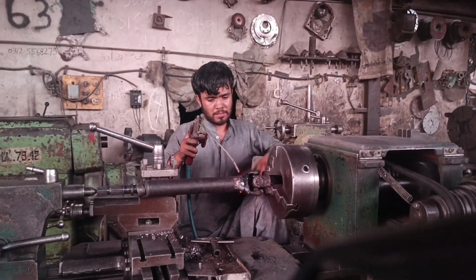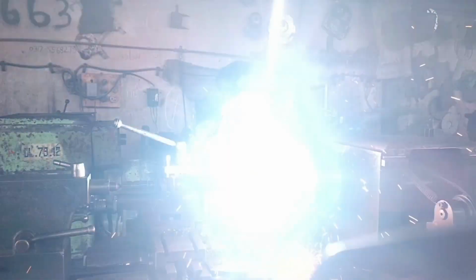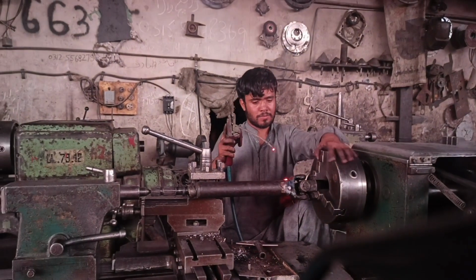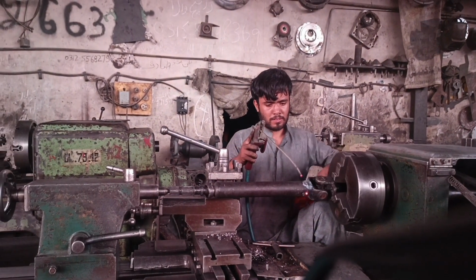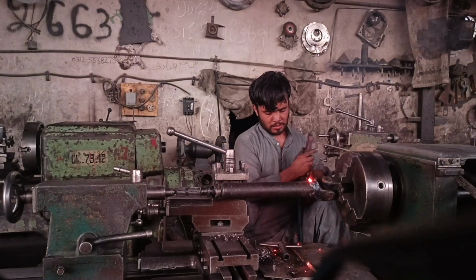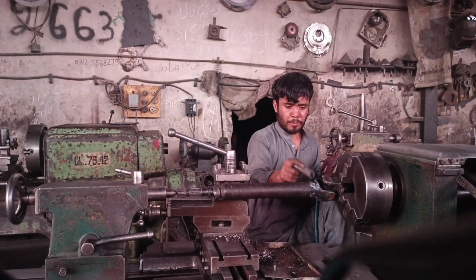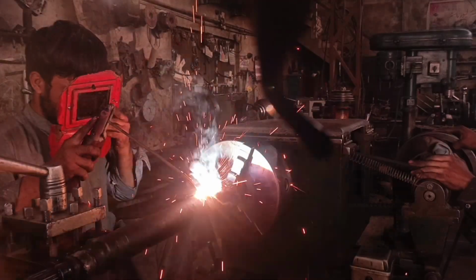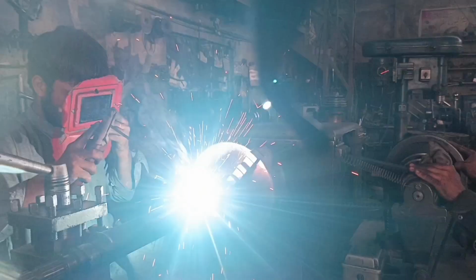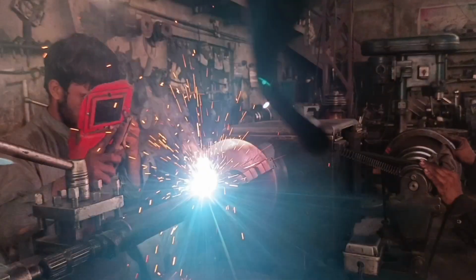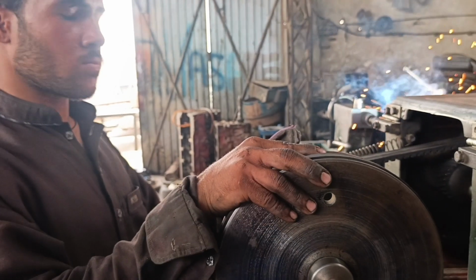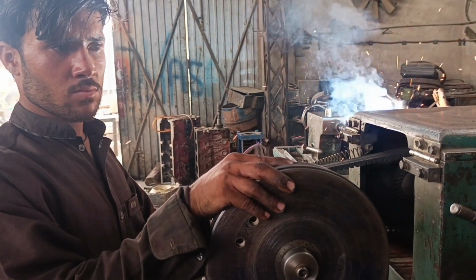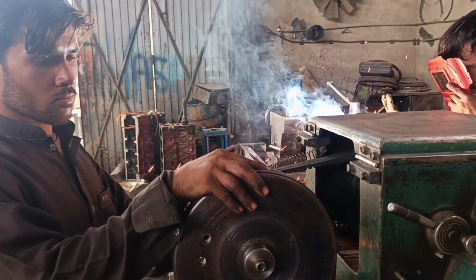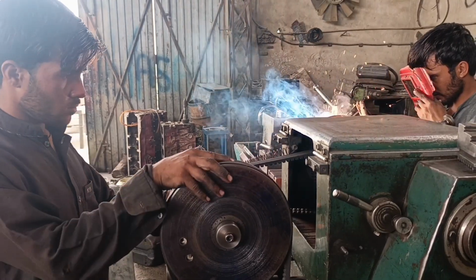The welding machine is then adjusted according to the material and wall thickness of the drive shaft. The correct voltage, current, wire feed speed, and shielding gas flow are selected to produce deep penetration without overheating the metal. A suitable filler material is chosen to match the strength and properties of the original steel. These settings are carefully verified because they directly affect weld quality and the service life of the repaired component. With everything prepared, the welder begins the final weld.